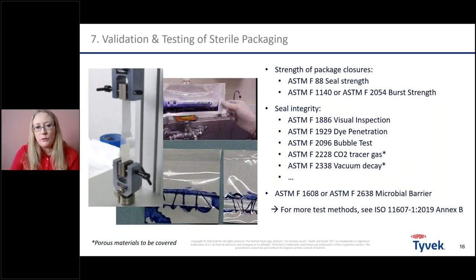Then you need to evaluate seal integrity, or integrity of the packaging. And here there are different tests. What is usually done a lot is, of course, dye penetration testing, ASTM F1929, or also bubble testing, which is a whole package test, a little bit more cross-leak, but good post-transportation, for example. And there are also new tests, vacuum decay, etc., which are on the market. And not to forget, it's not only about integrity, but also microbial barrier before and after sterilization, so the filtration capability of the porous material part. You can find more test methods in ISO 11607.